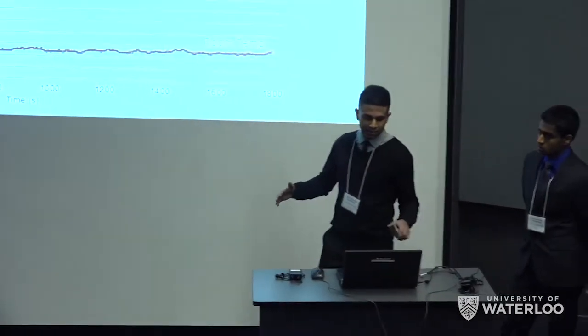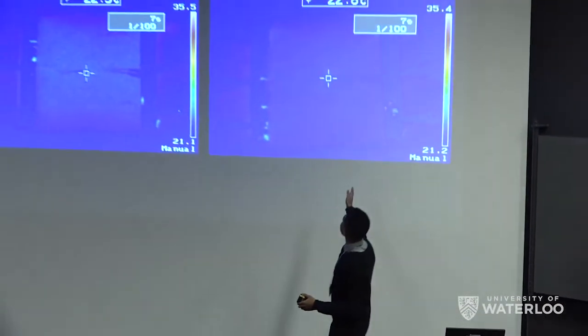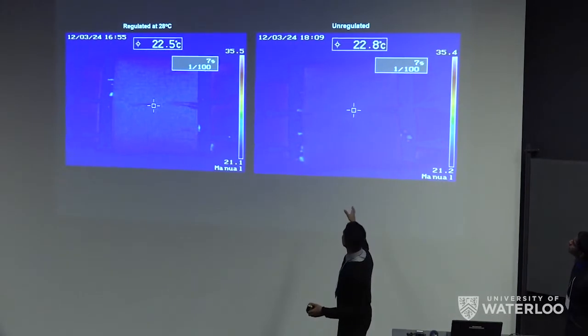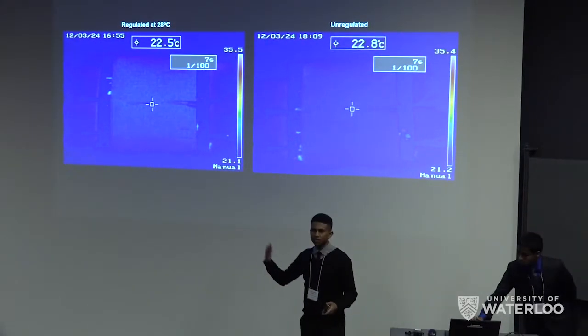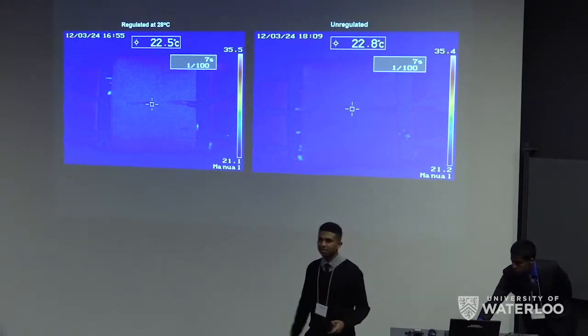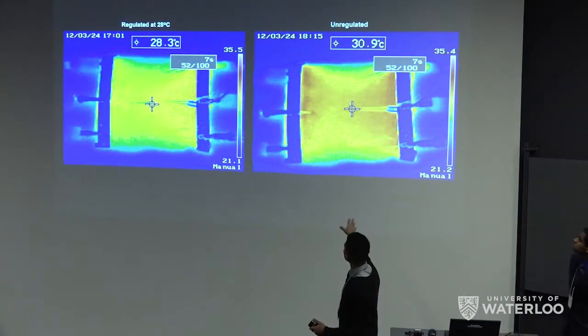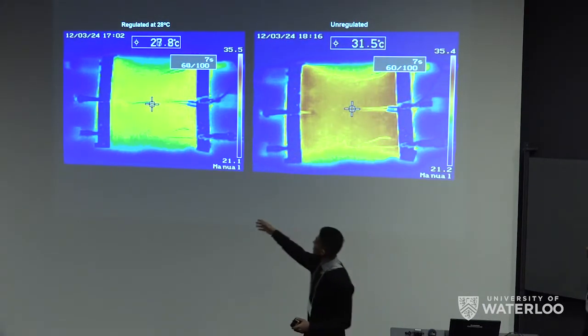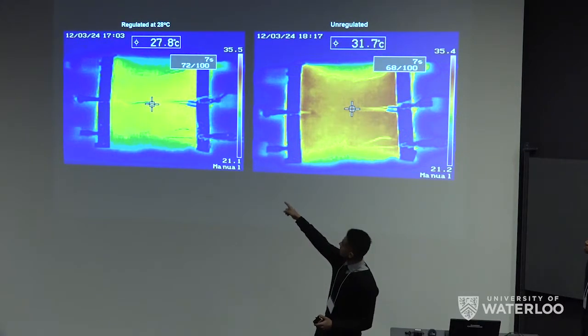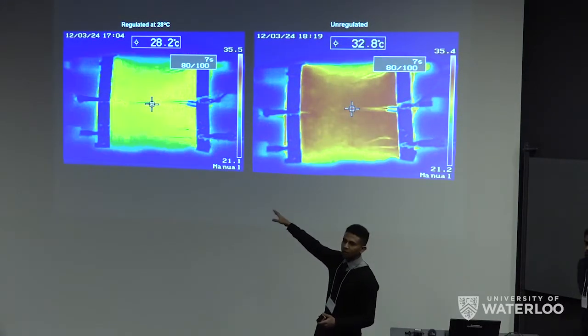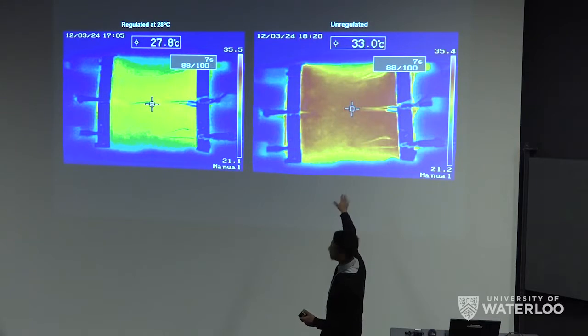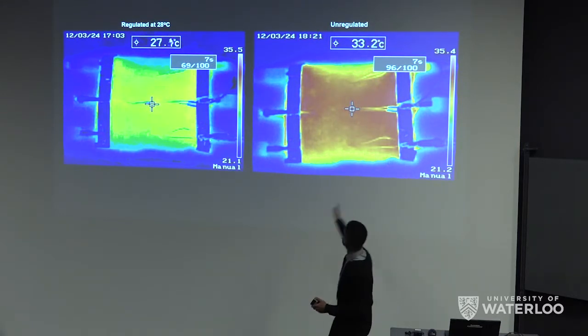Next, we just have some thermal imaging that I was talking about. What you can see here on the right is our unregulated thermal map, where the temperature is just going to be increasing indefinitely, in unregulated amounts. Whereas on the left, you see that we have a set temperature of 28 degrees Celsius, and it's just going to hover around that value, while in this case, it's just going to keep increasing upwards of 33 degrees.